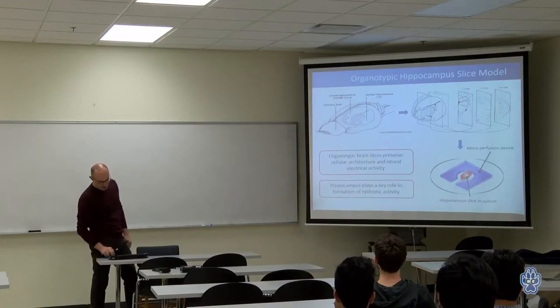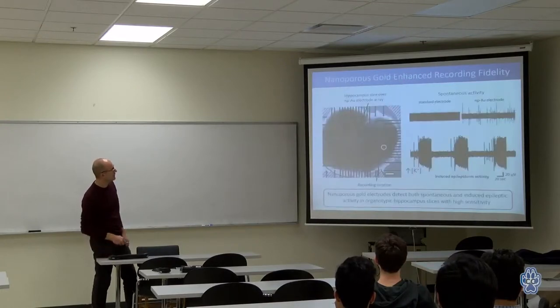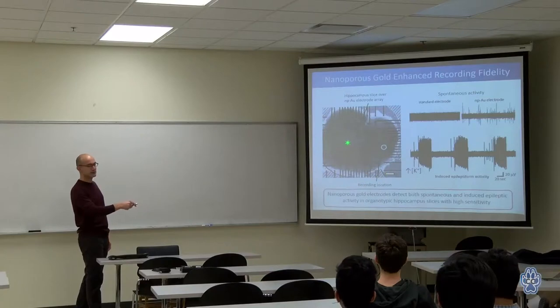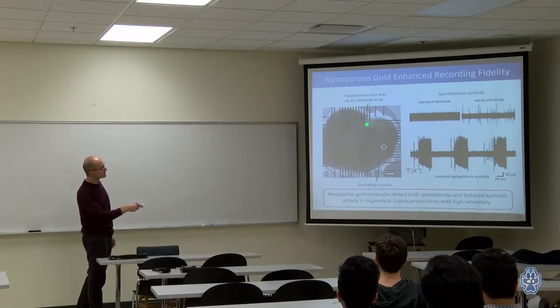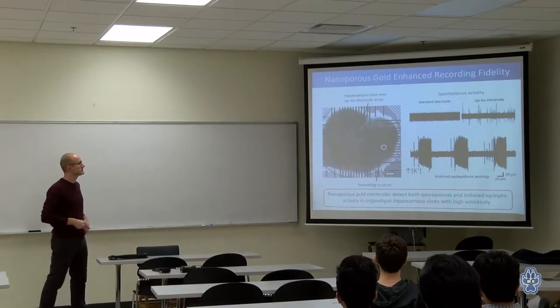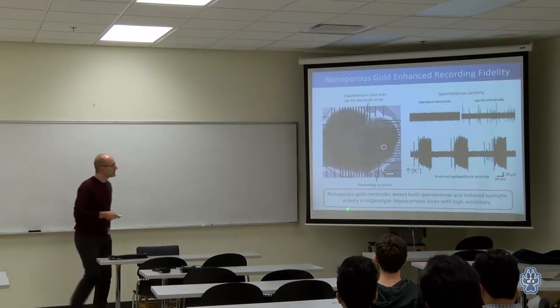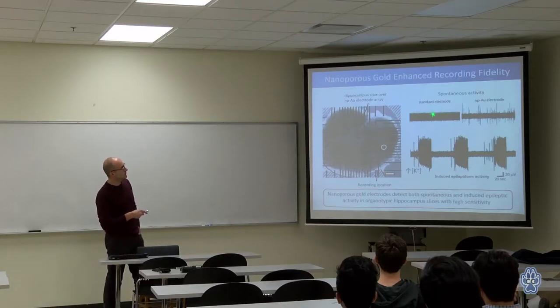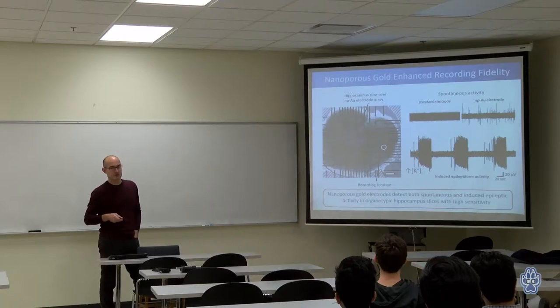Anyways, you get the organotypic brain slice, and then you place it on that electrode array that we built. So this is an organotypic brain slice you see here. And these electrodes are 200 microns apart, 30 microns in diameter, and they're made of the porous gold. What you see here is if you look at the electrophysiology, so the electrical signals the neurons are putting out. This is for a planar gold surface. This is for a porous gold surface.